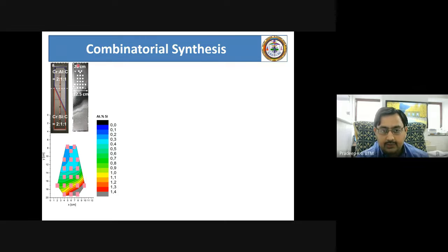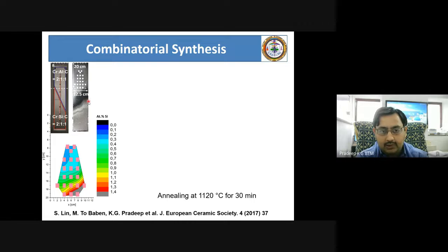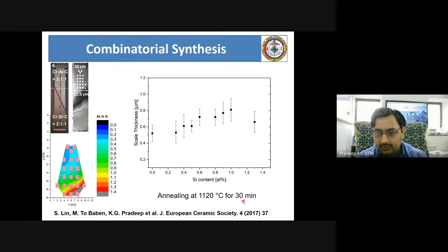This represents the region where all of these individual squares are shown with their silicon concentration. That means at the top of this first substrate you will have no silicon. As you come down to the middle part, you get a maximum of 1.4% silicon added to this chromium aluminum carbide. Now you look at their properties, which means all of these samples were prepared at the same time, at 1120 degrees for 30 minutes. You can see the amount of scale, that is, the oxide scale formed in the atmosphere during this annealing treatment, and the layer thickness is plotted as a function of silicon content.